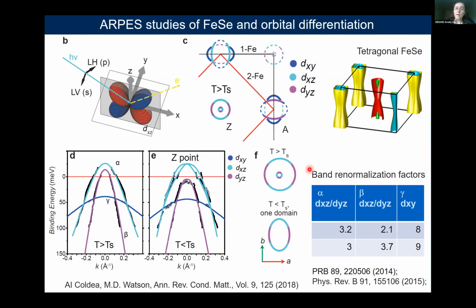Furthermore, the studies have allowed us to determine the renormalization factors associated with the different orbital characters. And here is an example of, actually, these are the points extracted from the data, high temperature. So these are the band dispersions, the different colors correspond to the different orbital characters. This is in a tetragonal phase. And we have alpha band, the outer hole band, and then we have the beta band, the inner hole band. And the renormalization for these 2 bands with mixed dxz and dyz character is about 3 to 4.